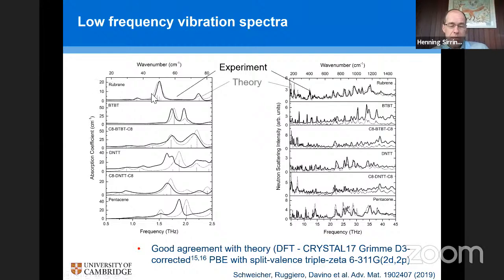And then you have many, many modes, these hundreds of modes. In the neutron spectra here, you can see them as you go to higher frequency. Of course, they acquire a more intramolecular character. The carbon-carbon stretch vibrations appear at higher frequency here. But essentially, you'd have to take all these modes into account if you want to understand how the thermal disorder is generated in these systems.